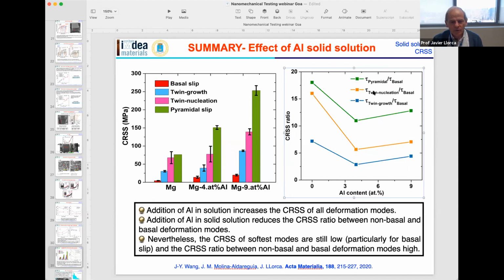And then we can look at the effect of the anisotropy. This is the ratio between non-basal and basal slip for the critical resolved shear stress. As you can see, when you add a little bit of aluminum, you reduce the anisotropy for all the deformation modes, but there is still a strong anisotropy between non-basal and basal slip modes. So with adding aluminum, you cannot significantly reduce the plastic anisotropy of magnesium alloys.